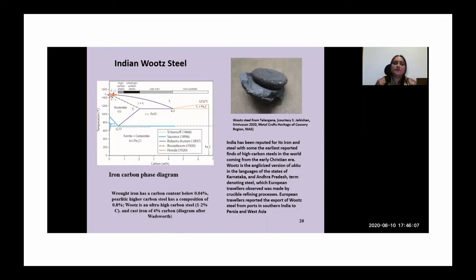And there have also been empirically undertaken experiments where, at different control situations, they attempted to alloy different constituents to each other to see what sort of structure forms. And then there's a whole set of the handbook of metallurgical structures, which has been extensively published. So if you want to get a certain kind of alloy, for instance, you just have to try it in the laboratory. And then you look at the metallurgical structure and you can compare it with the published structures. And it gives you an idea of the composition, even without undertaking an analysis and things like that. So it's very useful that way to understand the phase diagrams.